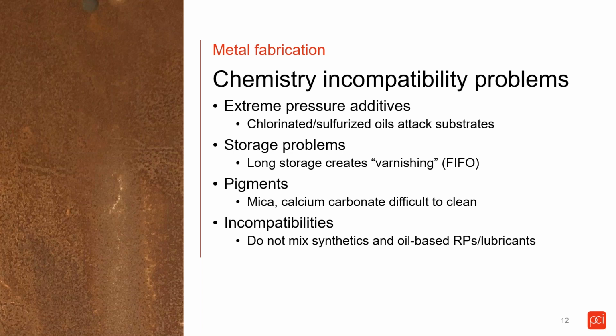Other storage problems are something that we call varnishing, which is if a lubricant's sitting on a shelf for too long, it begins to lose its properties. It starts to get really, really thick and heavy, and it's pretty much impossible to clean off. So it's basically like a varnish. And the best way to maintain and avoid these first two problems here is first in, first out. Simple as that.